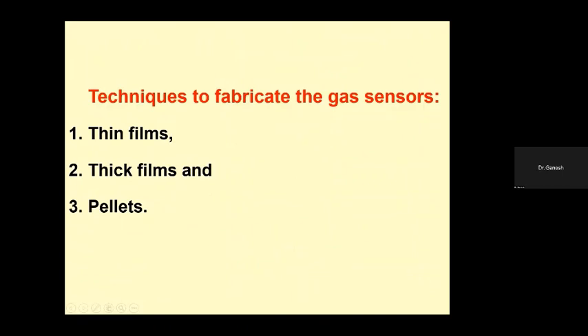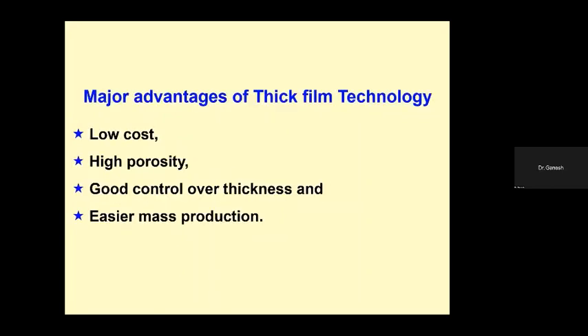Many techniques are available to fabricate the gas sensors. They are thin films, thick films, and pellets. Out of which we prefer thick film technology because it is low cost and has high porosity. As gas sensing is a surface phenomenon, we need porosity on the surface of the film, which we can manipulate by using thick film technology. Then there is good control over the thickness of the film. We can fabricate films of different thicknesses, and easier mass production is there.